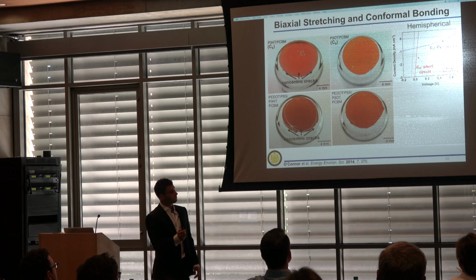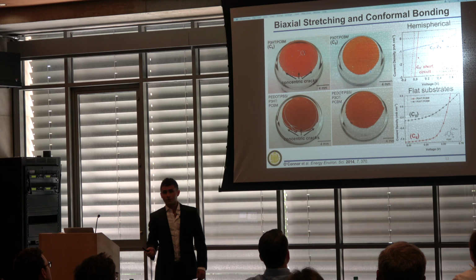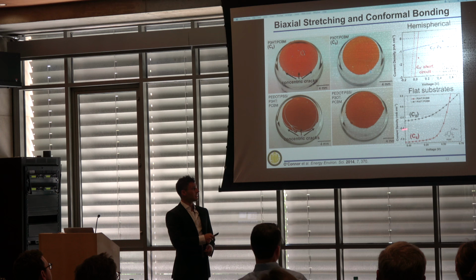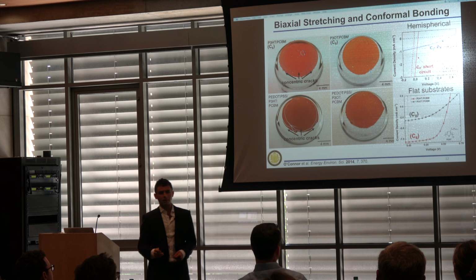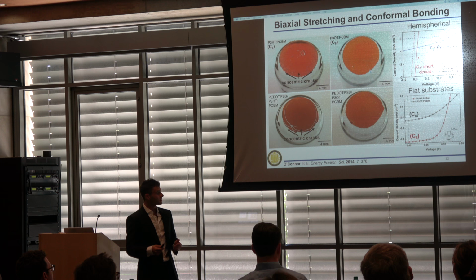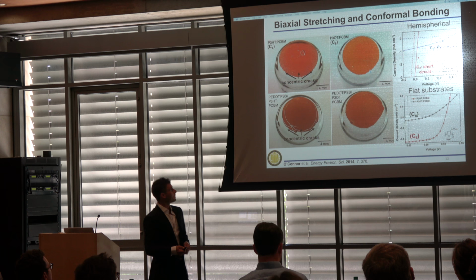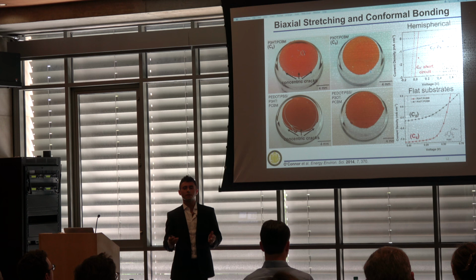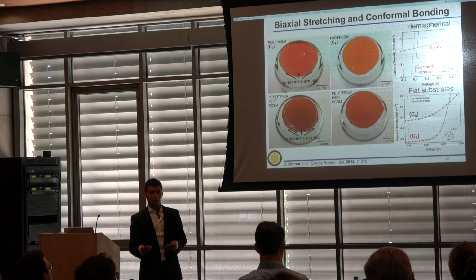So this isn't just noticed on the hemispheres. If you make them on flat substrates, C8 is about 3 times less efficient than C6. So C6 gives about 3.5% efficiency. C8 is only about 1%. So it seems like even though we've gained some mechanical resilience and some elasticity in our material, we've lost electronic performance. So we wanted to see if we could co-engineer both parameters in a single material, or if these types of effects were at odds.